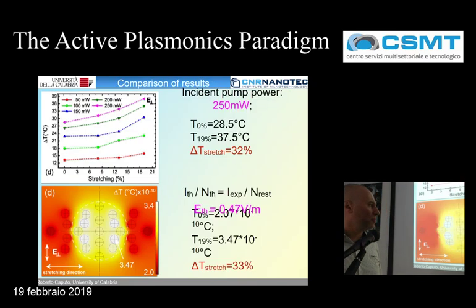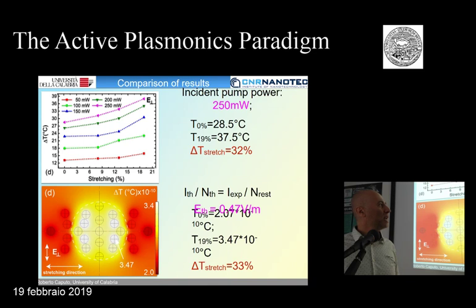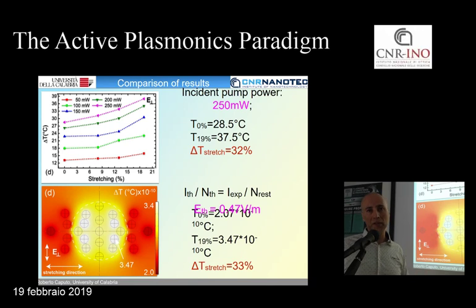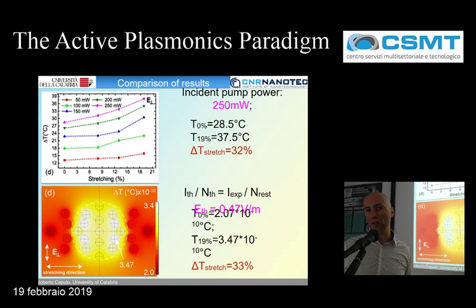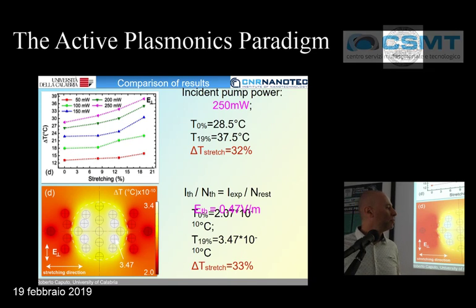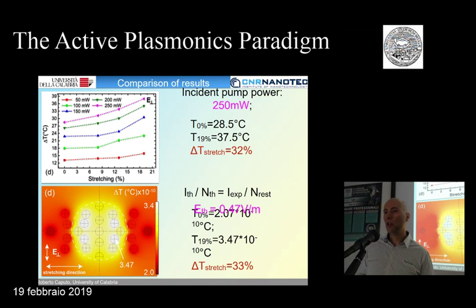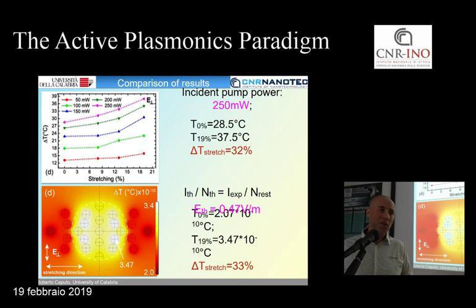I'm sorry for this because I think the change to PowerPoint didn't work very well, but in principle this slide says that if you make a proportion between the field you use for the experimental case and the one that we used in the numerical simulation, a proportion made with the number of particles that you expect to have in the experimental sample and in the numerical case, you get almost the same increase of temperature in the numerical and experimental case, giving some kind of quantitative confirmation to the result.